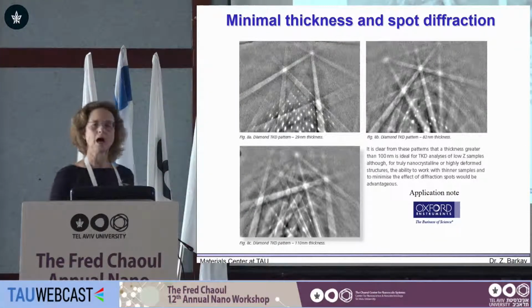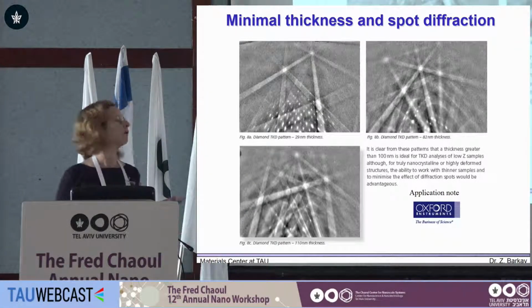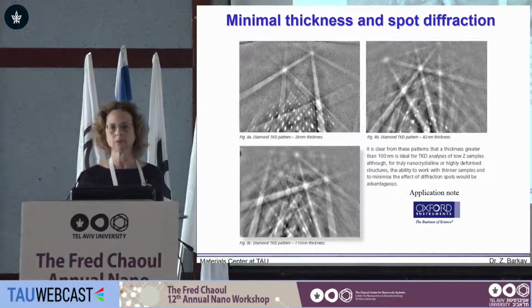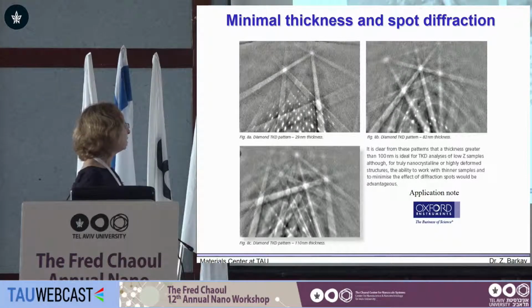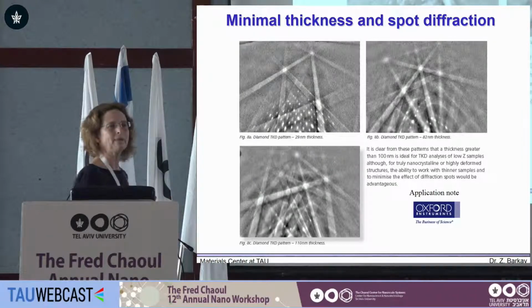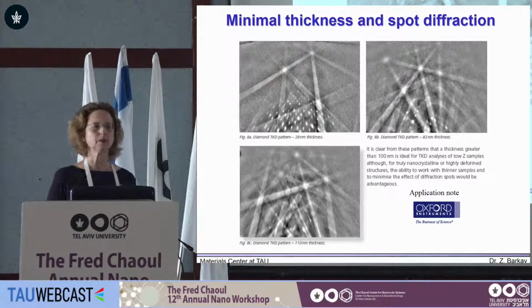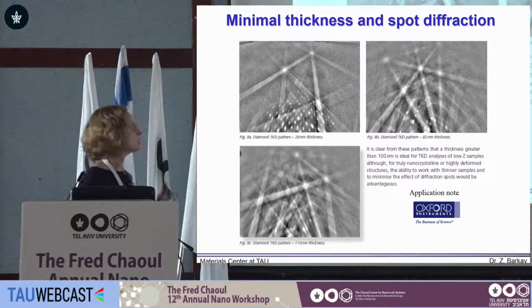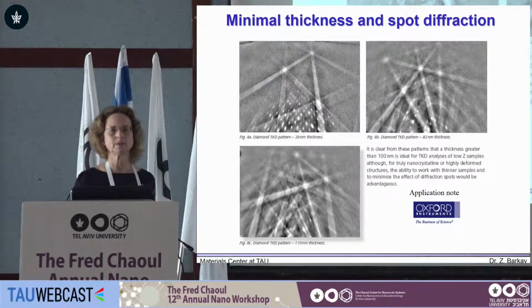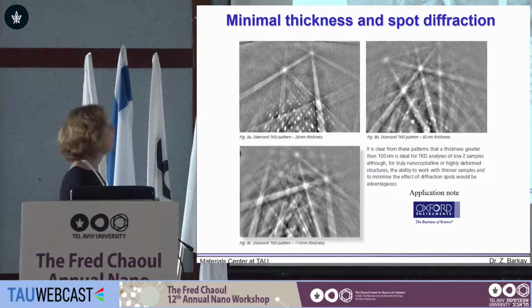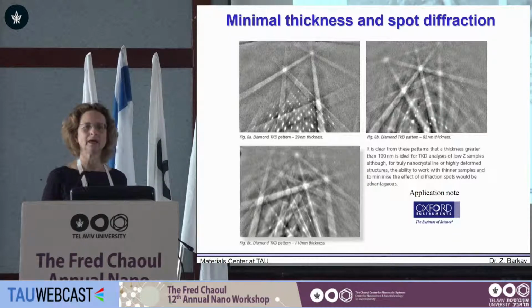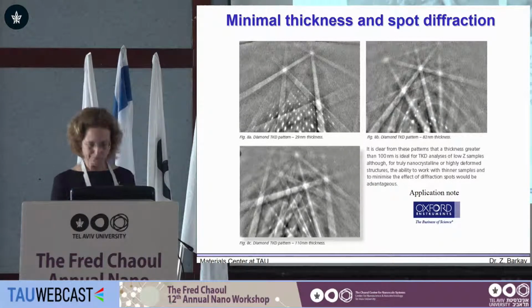And this is very well emphasized experimentally here, although it is also well understood theoretically. This is about a 100 nanometer diamond film where we have a very nice Kikuchi pattern, and when we thin it down to 30 nanometers, we get this spot information which is not very well resolved and actually interferes with what is called the Hough transform for understanding or recognition of the line patterns in the Kikuchi.